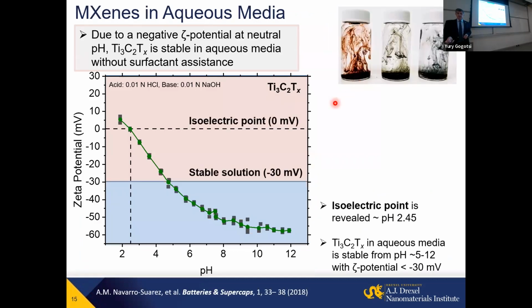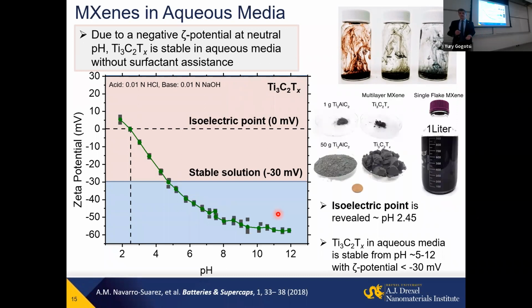And it's all possible because of the high negative surface charge, zeta potential below minus 30 millivolts, which allows us to create a stable colloidal solution in water without adding surfactant or anything. And this is again a big difference compared, for example, to graphene, where you can work with graphene oxide in water, but if you want to get it back to the conductive form that is usually used in most applications, you need to reduce it, or you have to use surfactants or additives.